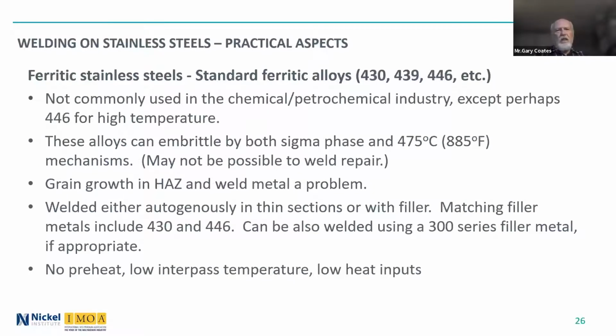If we move on to the higher chromium ones, 430, 439, 446, they're not so common in the chemical, petrochemical industry, perhaps the 446 for some high temperature applications. They can embrittle by sigma phase in this 475-degree embrittlement. And why I mention that is that if you're trying to do a weld repair on ones that have been in service at that temperature, they may not be possible to weld repair. They may be so brittle that you cannot weld repair them.